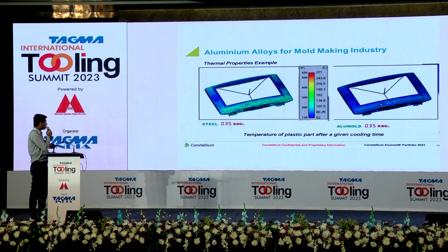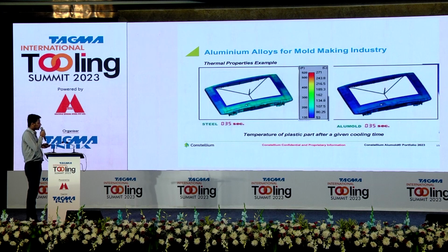Yeah, this is a component after 35 seconds of cooling. The left-hand side shows the steel mold and the right-hand side shows the Alu Mold 500. After 35 seconds in tool steel, the part will have cold spots as well as hot spots, where the warpage will be high. In the alu mold, the temperature distribution is more or less uniform, thanks to the high thermal conductivity.